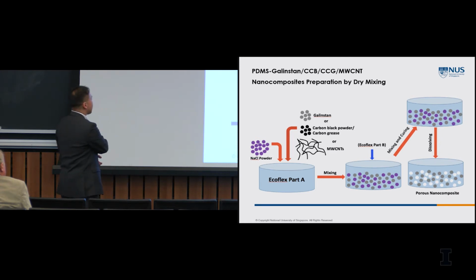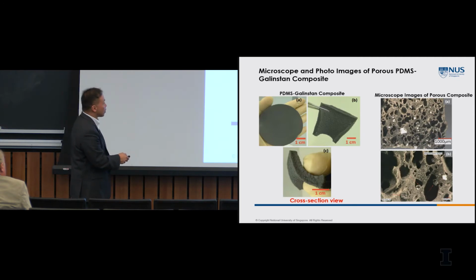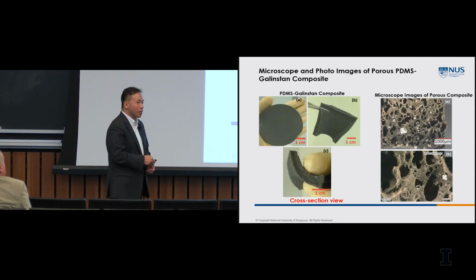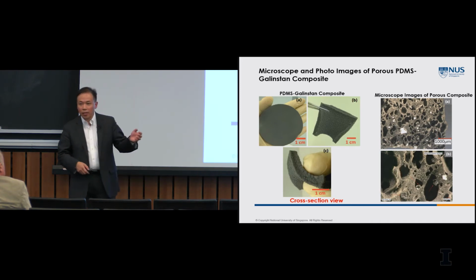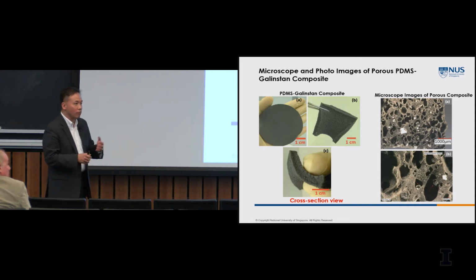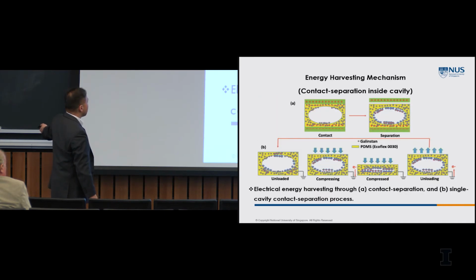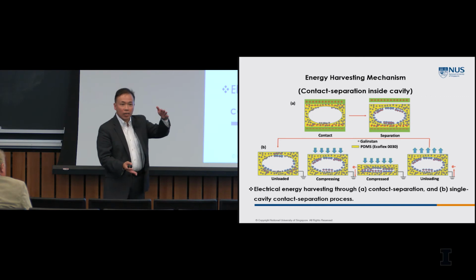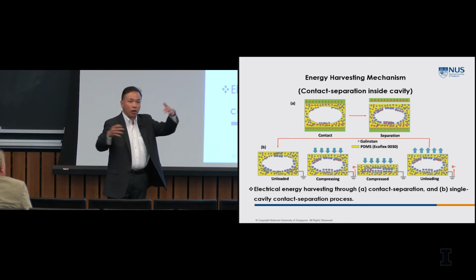So it looks something like that. This is the material. These are the pores. You can see some of the leftover salt that's in there. The reason why it's black is because of the oxidized gallium oxide that forms in the material itself. So basically, when you compress this material, the pores touch within the material itself, and it generates charges within it. These charges are then mirrored into a conductor on the outside, and then carried on as current.